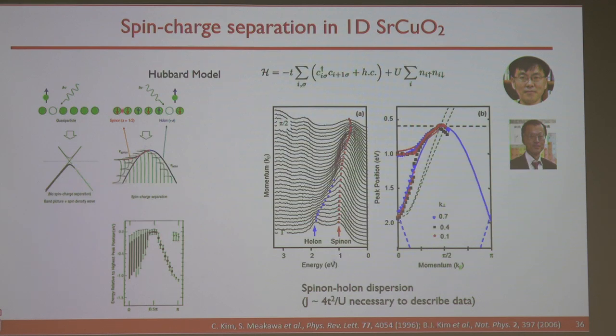But what we want to know is, if you dope two holes, what about the interaction between the two holes? This experiment was done in an insulator. Effectively, you dope the system by the photoemission process. You take out one electron, you dope in a hole, and we study the dynamics. And we have tried to grow single crystals of this one-dimensional system, but you just cannot dope them. They always stay insulating.